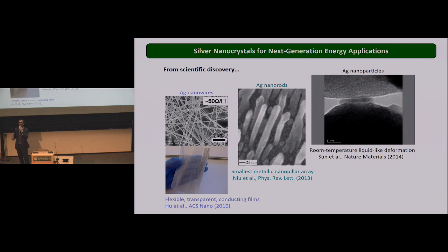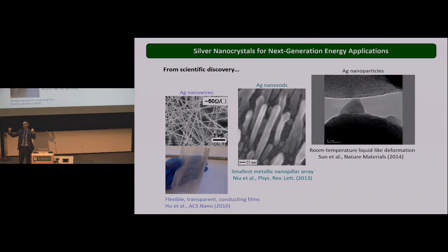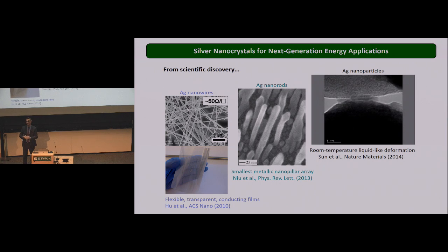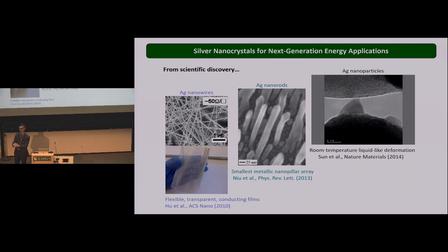That's the big advantage. Still, to achieve that, you need to, in simulation, deform the wire with a strain rate that is 10 orders of magnitude larger than in experiment. So can we match the strain rate in experiment and simulation? It may be possible, but it will require maybe a PhD student who wants to develop that. That will make a huge progress in this area, okay? That's not what we did here.